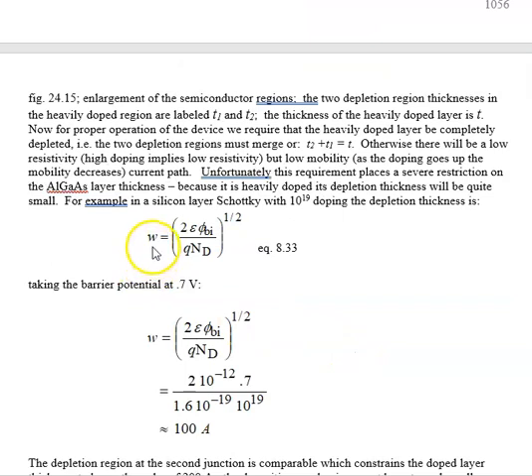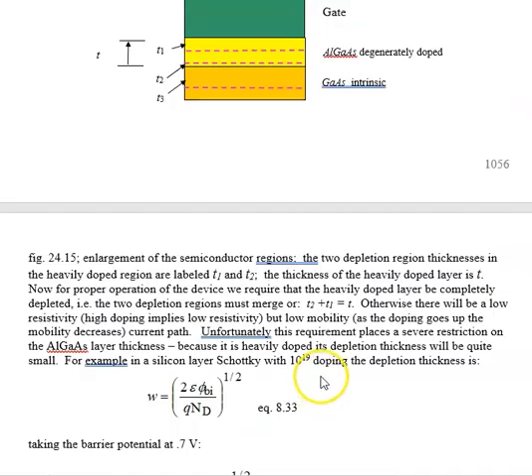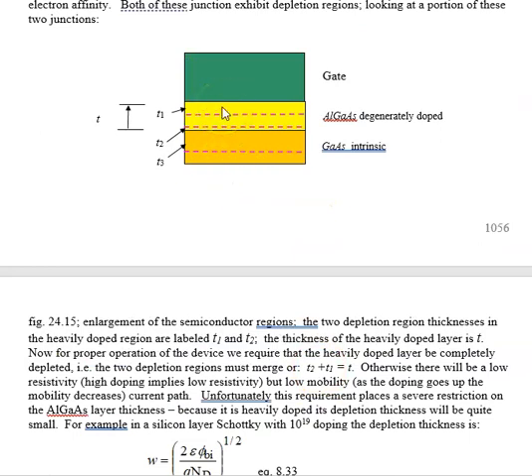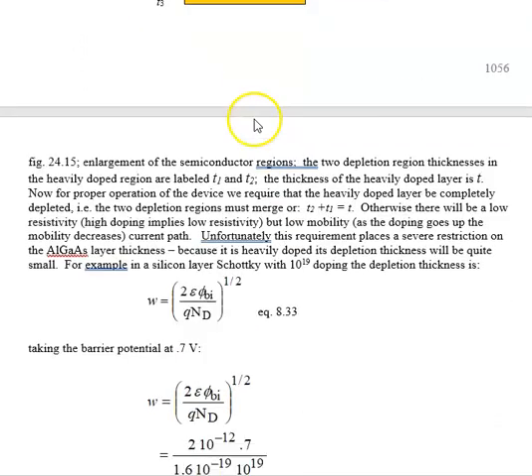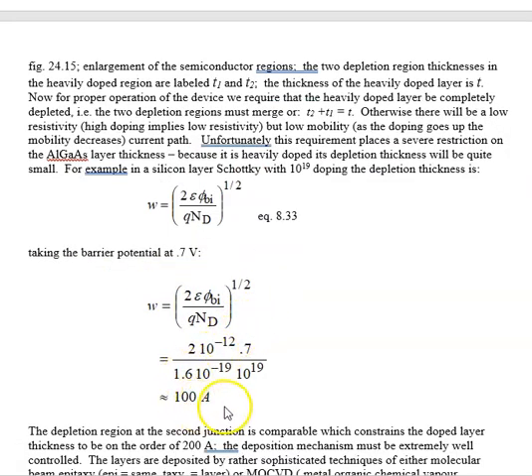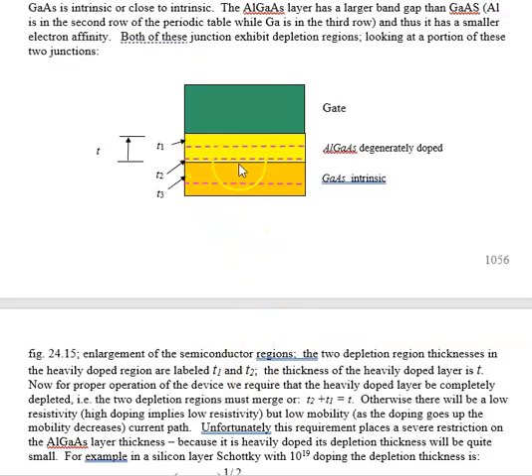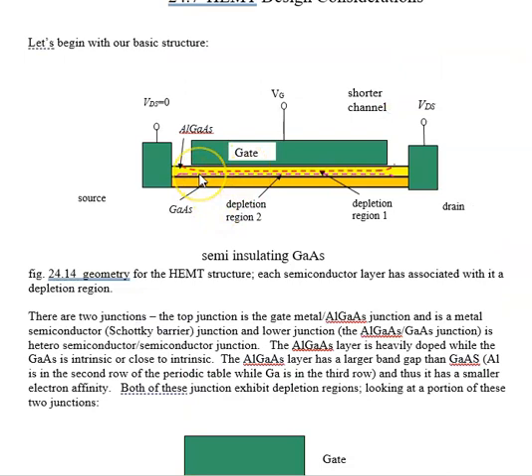We find that the depletion region is about 100 angstroms, and that is going to be the same for both T1 and T2, because the depletion region is always on the lightly doped side of the p-n junction. The depletion region, if it's a metal semiconductor, of course, is on the semiconductor side. So this would be the depletion region for a Schottky barrier doped to 10 to the 19th, and it's about 100 angstroms, and that is about the same as the depletion region on the, quote-unquote, lightly, or I should say the heavily doped side of this p-n junction.